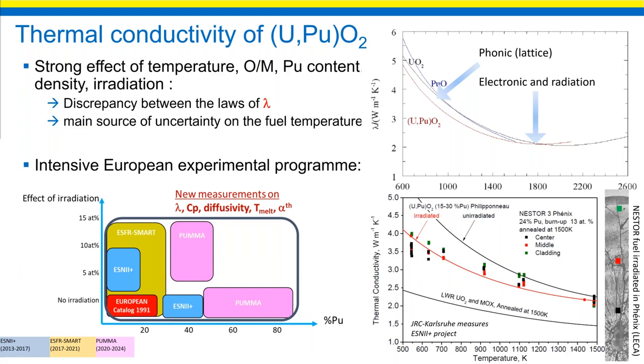So this thermal conductivity is higher than expected after this burn-up, and we have several possible reasons: a higher temperature during the irradiation that led to less damage effect, a loss of most of the fission products that could affect the diffusivity, like cesium, an increase of the metallic fission products that enhance the conductivity, and less porosity, mainly due to the gas release. We are still working on the interpretation of these data. So next slide, please.